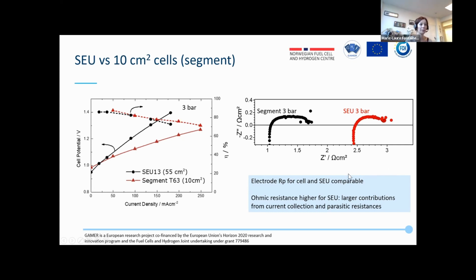So when we did impedance spectroscopy measurements, we found out why. Here you have the impedance spectra for the segment, and here for the SEUs. What you can see is that the electrode performance for both samples is fairly similar. However, we have a huge increase of the ohmic contribution for the SEUs. This is due in part to the fact that when we make the SEU, we have integrated many more interfaces, so we also have to optimize some current collection there. And we also had some parasitic resistance with the setup that we are utilizing when testing these SEUs. Overall, that gave us input on where to further focus our studies in terms of material. And as you can see here, it was on current collection and interfaces.